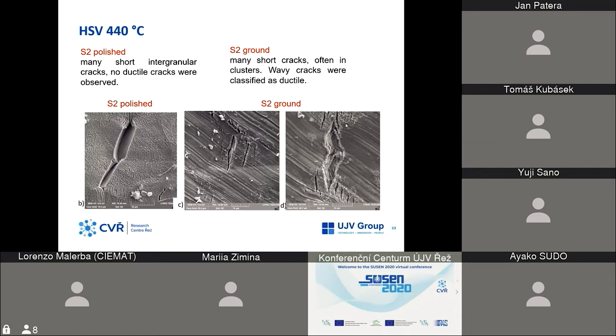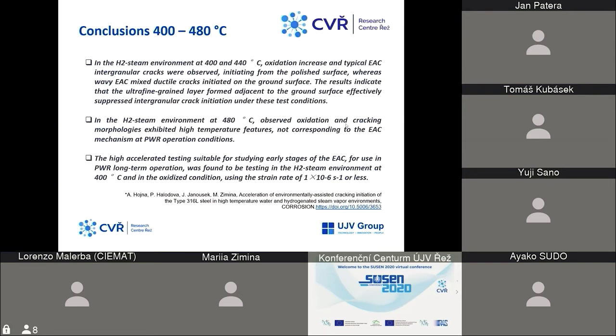So as we can see, with the high temperature, we observe cracking, and this cracking is more similar to the one which is observed under operation conditions of the power plant. So to conclude, we also performed more testing at different temperatures. The detailed results are presented in our paper, which you can see down on the slide.